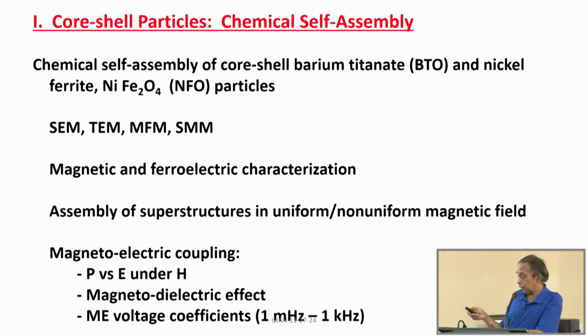And of course, you have to study the nature of the magnetoelectric coupling. For that, we use P versus E under H, the magnetodielectric effect, that is, the change in the dielectric constant when you apply a static magnetic field, or also the ME voltage coefficient.